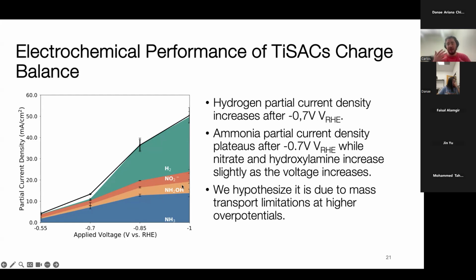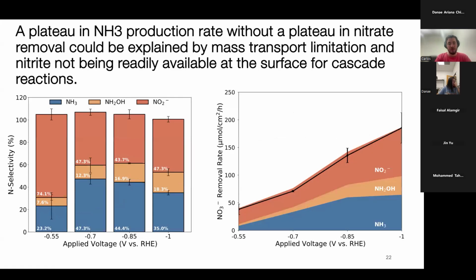And we hypothesize that some of those nitrites and hydroxylamines that are normally intermediates to ammonia end up getting desorbed from the catalyst surface and they don't get reabsorbed because they dilute into the electrolyte, and we have these thick, almost like 1-inch or half-inch chambers that don't have any flow. So we think that we can improve this now that we're moving to flow type reactor architectures. So having serpentine and flow management channels should allow us to have better mass transport there.